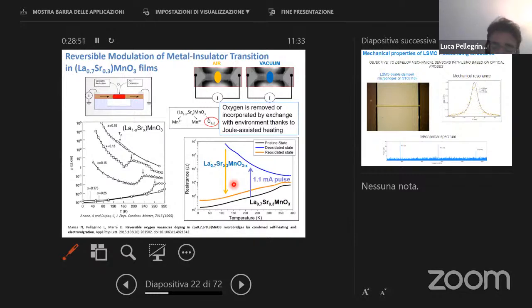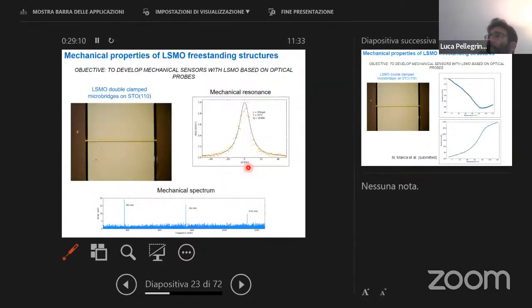I showed you before, you can change the ratio of the domains in vanadium dioxide. This is just the phase transition, but in this case, you can even change the stoichiometry of oxygen. So this is another example of the advantages of making freestanding structures with these oxide epitaxial films.